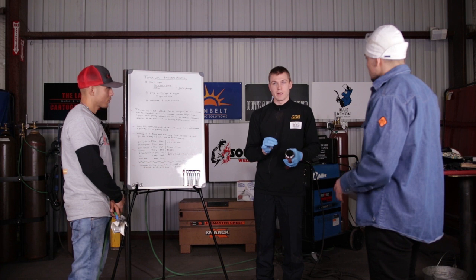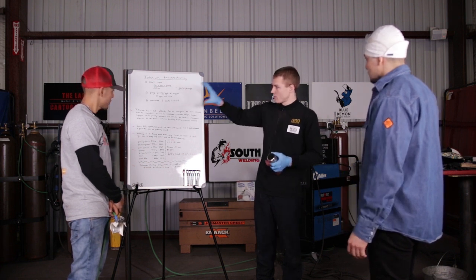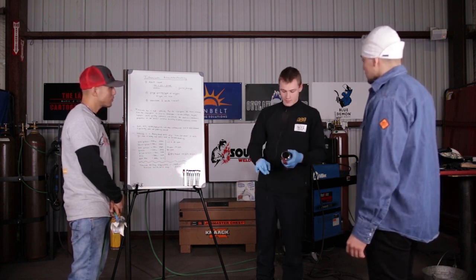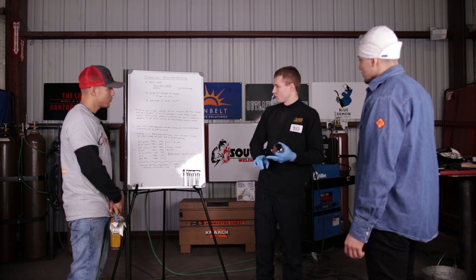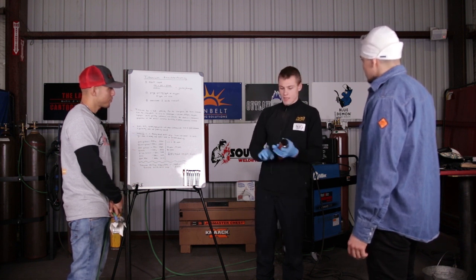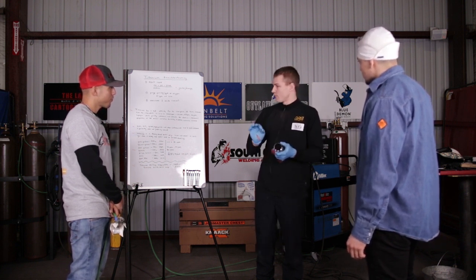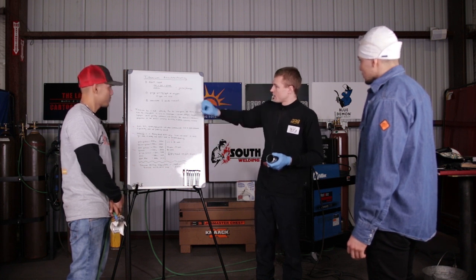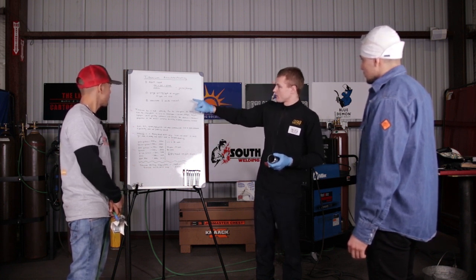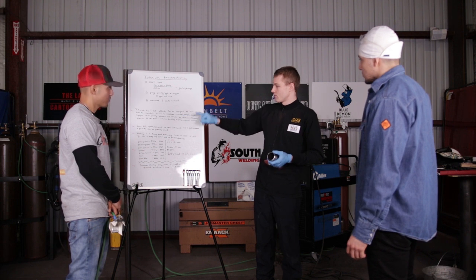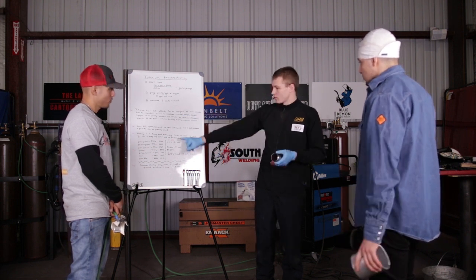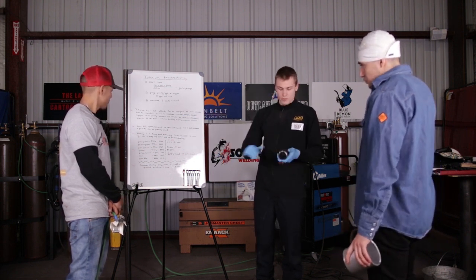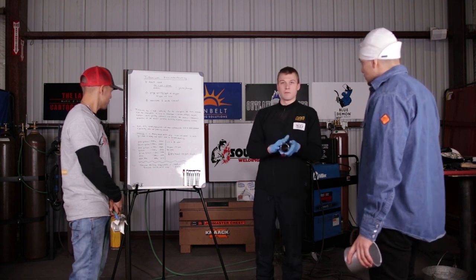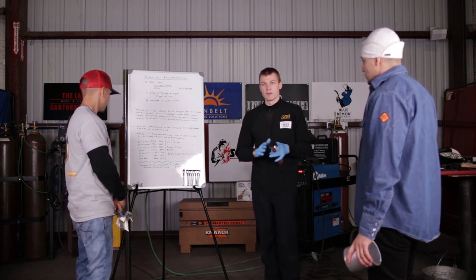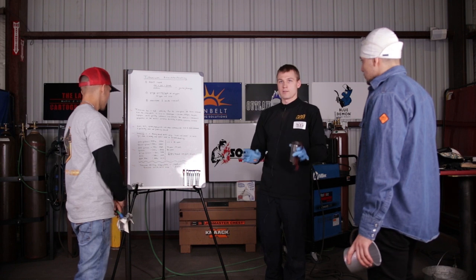Essentially, if you do everything right on titanium, including applying this theory and knowledge to the other metals, stainless, duplex, super duplex, nickel alloys, etc. If you do everything properly, you follow your heat input, proper purge quality, parts per million of oxygen, proper cleanliness and oxide removal, and less than 25 parts per million, the deposit of metal will be silver and you'll have no heat tint. Everything will be silver without any heat tint or oxidization.